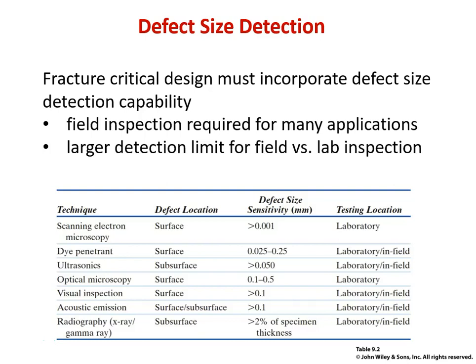So this chart is out of the Callister textbook, and it just gives you a little order of magnitude idea of the flaw size detection capabilities of different lab and field methods. And this is probably out of date enough at the time of this lecture recording, which is January 2019. Some of these have probably gotten a bit better in terms of the field tests, but something like an SEM, which would probably be more applicable for destructive evaluation, something that's already failed, which we're trying to prevent, you could have something that's on the order of a micron.